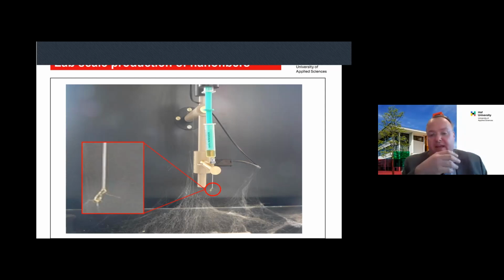This dilution of the electrical charge carriers leads to the effect that we have a stretching of a jet, of a pre-fiber, and next to this we have evaporation of the solvent, and therefore we have the formation of the nanofibers. So the dilution of this charge carrier concentration, because you know, if you have these uniform charge carriers, you have a strong repulsion between all the charge carriers, and therefore, of course, you have this jet formation to this side or to this side.